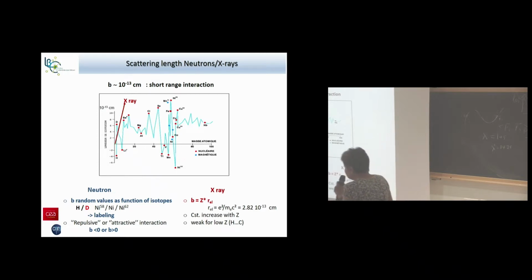So neutron scattering is very important for soft matter because, as you can see, there are huge differences between the scattering lengths of hydrogen and deuterium. This is important since with polymer systems we can label molecules and change the scattering power of the molecule, the scattering length of the molecule, the amplitude of the scattered wave, when the radiation hits the deuterium atoms.